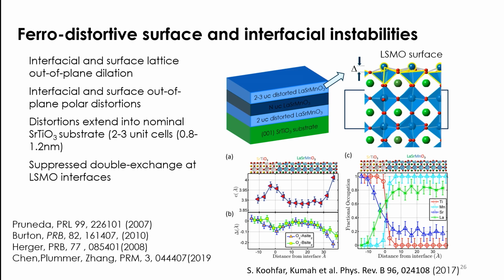But the main thing we found was that at the surface of these films, so this was a 10 unit cell thick film, which was above the transition thickness limit. Because we were able to very precisely measure this atomic displacement, we found out that the manganese at the surface was displaced upwards relative to the oxygens by a very, very small value. So the displacement is plotted here from the surface to the interface with the STO. The displacement starts off at 0.2 of an angstrom, which is very, very small.